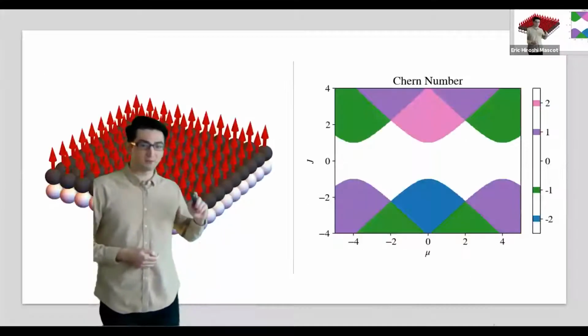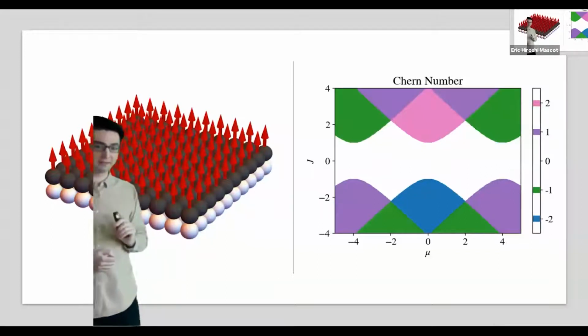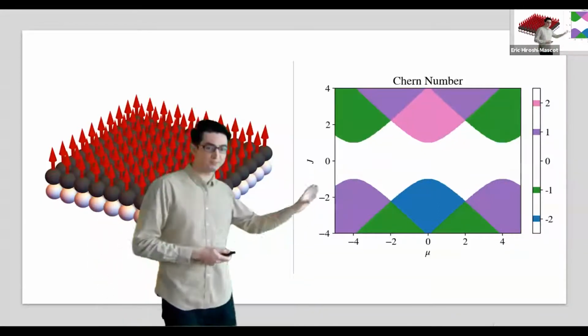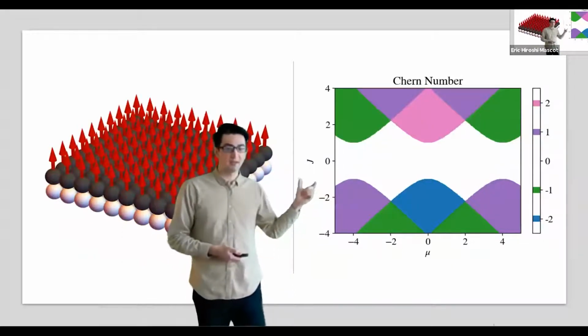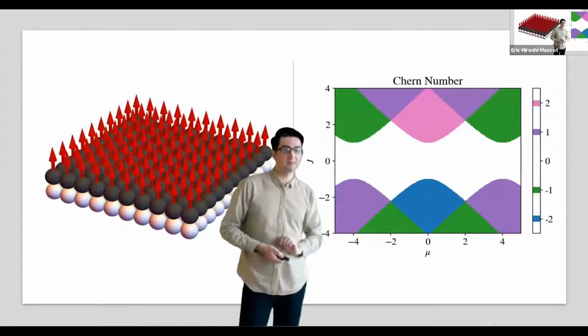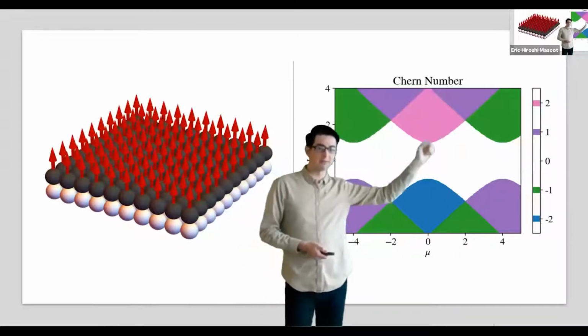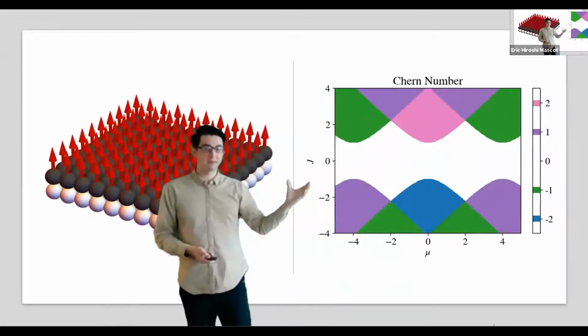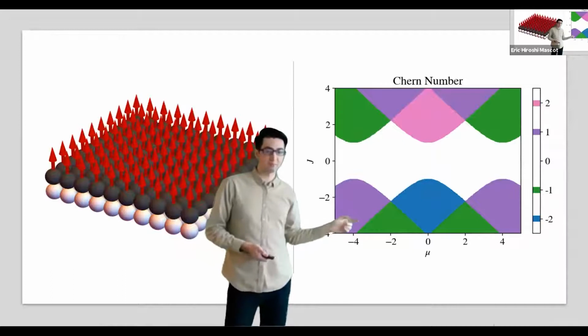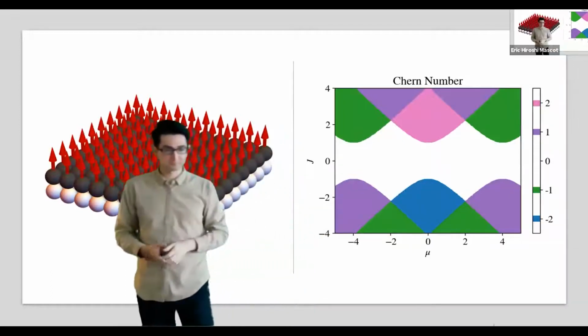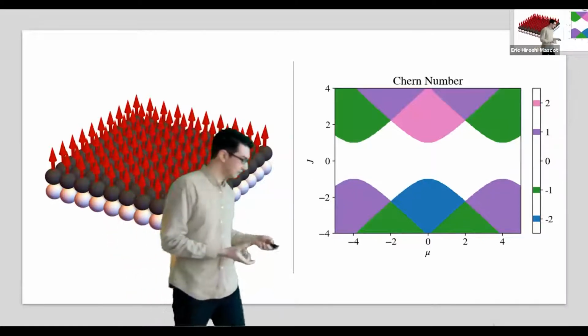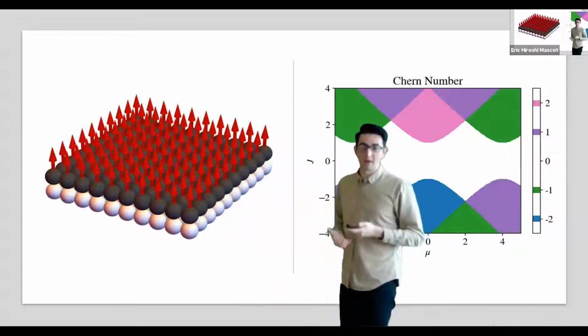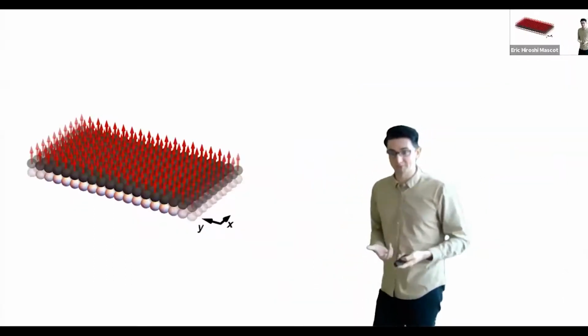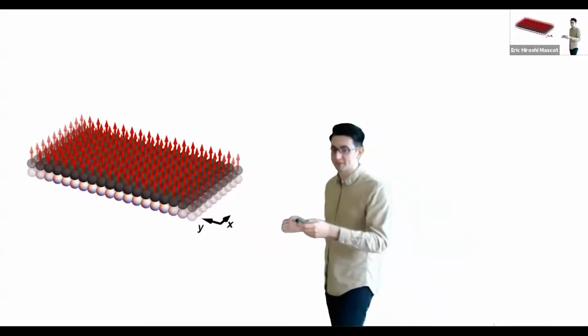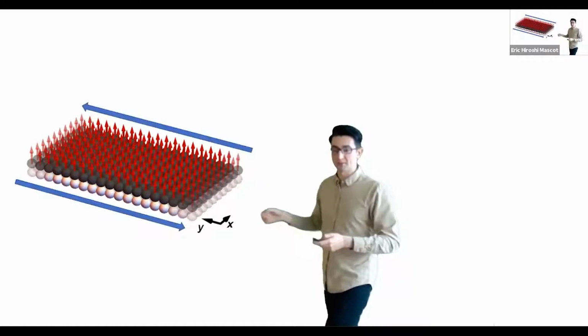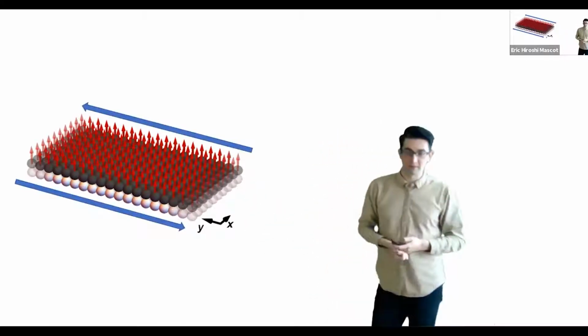Okay, so we can take the thermodynamic limit and calculate the topological invariant. And for different parameters for the magnetic exchange and the chemical potential, we get these different topological phases. Here it's -1, 1, and 2. And if we flip the sign of the magnetic interaction, then we flip the sign of the Chern number to 1, -1, -2. And we want to study the boundary states, these zero energy Majorana modes. So we put this in a ribbon geometry, and we make it finite in the x direction, but infinite in the y direction. And so on the boundary, we should get these chiral Majorana edge modes.